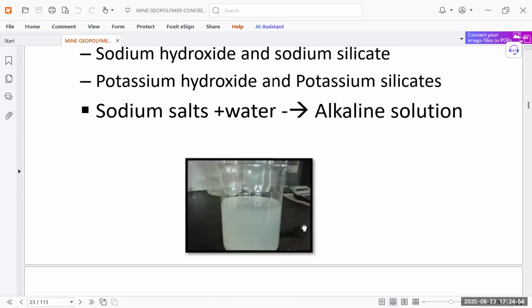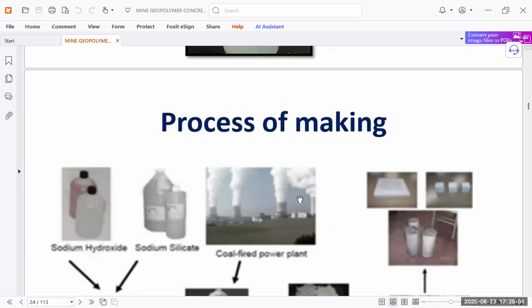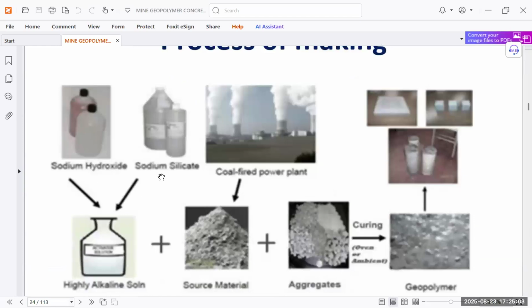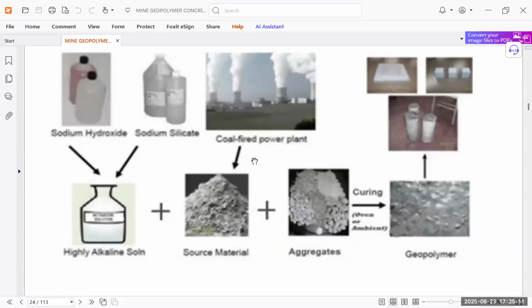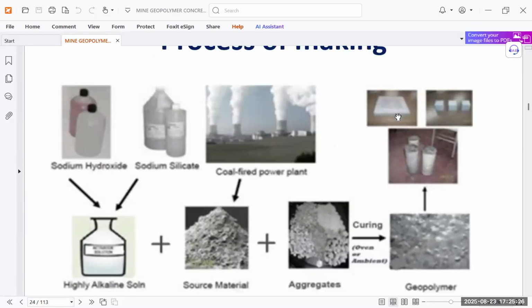After this reaction is done, the process of making is that sodium hydroxide and sodium silicate are mixed, and from the coal-fired power plant we get the source material. We mix the sodium hydroxide and sodium silicate solution, then we make a highly alkaline solution. The source material from the coal-fired power plant and the aggregates are used. Then curing is oven or ambient temperature curing. It is not water curing. Then geopolymer is made, and it is used for making cubes and other parts, similarly to how we do in other mixes. This is how its production is done.